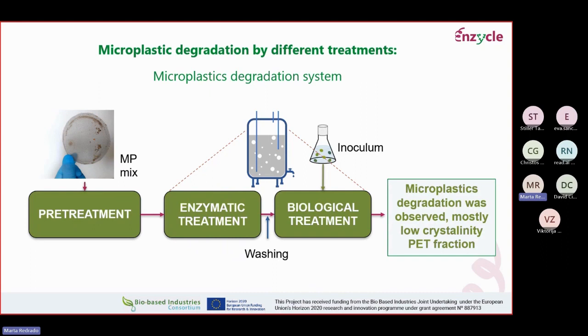And we indeed observed the degradation of microplastics to some degree, but well, to be honest, we were successful in the degradation of basically the PET fraction of the microplastics, right? We observed some modification of the structure of the polyolefins present. We analyzed these results with Raman, and this is how far we could reach. It is problematic when we are dealing with plastics that are not PET, and when you have plastics with high crystallinity.